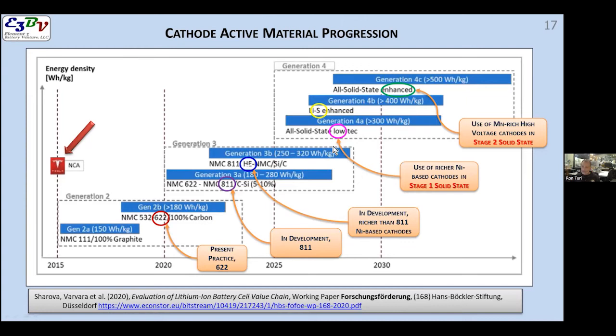And these things are all happening. But ultimately, if you get to the next set of generation products, you get to high voltage cathodes that are manganese based and can hold twice as much lithium per transition metal atom. Suddenly things really ratchet up. Plus they operate at a higher voltage, and the amount of watt hours that you have in there is the amp hours times the volts. So if you bring up the volts, you also increase your energy density. There are many ways to benefit.